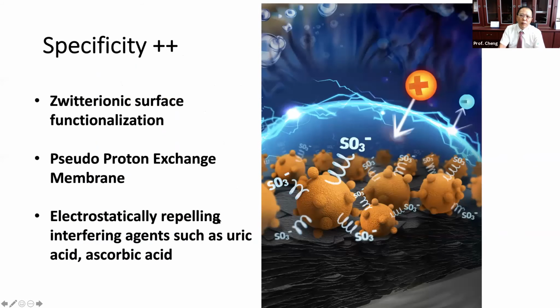Okay, so the novelty here is that in the urine we have many interferences like uric acid or ascorbic acid. All of these are negatively charged. So we try to use a zwitterionic surface functionalization. We have this negative ion tail surrounding the nanoparticle. This negative ion layer looks like a pseudo proton exchange membrane. Then the negative ions will be repelled to the solution, but the positive ions will go inside and react with our Cu2O.